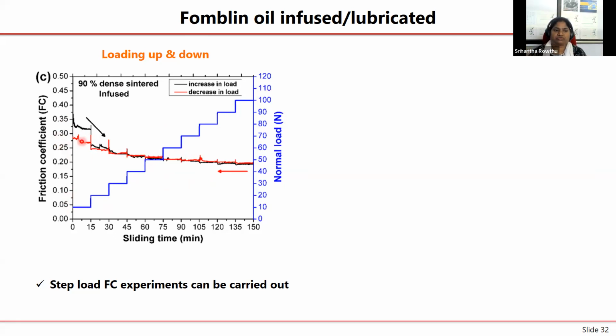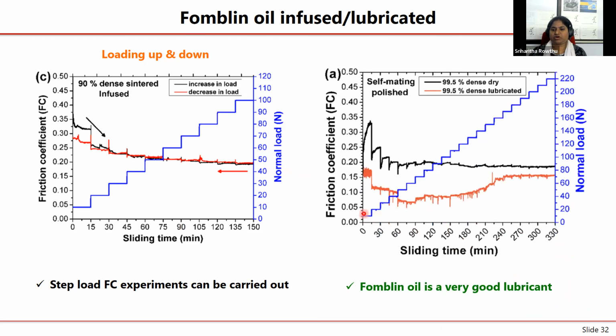So if you superimpose the friction coefficient curves, they are quite nicely matching except for the first 15 minutes or so. So in principle, one could do a pre-alignment of the samples by 30 minutes or 15 minutes or half an hour, that's pre-alignment. Then if you conduct your step load experiments, it's perfectly all right.